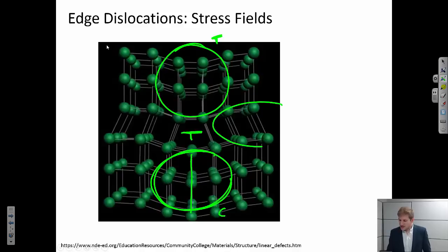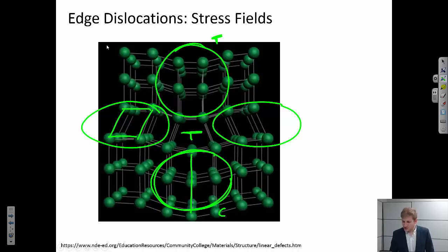The other thing that you can see is that we see shear to the left and the right. And the easiest way to see that is to just look at this unit cell here, and this unit cell here, right? And again, you can think about it in terms of compensating for this extra half a plane of atoms. So the bottom part is spread out a little bit relative to the top part, and that manifests itself in terms of shear in one sense off to the left side, and then shear the other sense off to the right side. So this is generally true. For an edge dislocation, we have a compression field, we have a tension field, and then we have two shear fields.